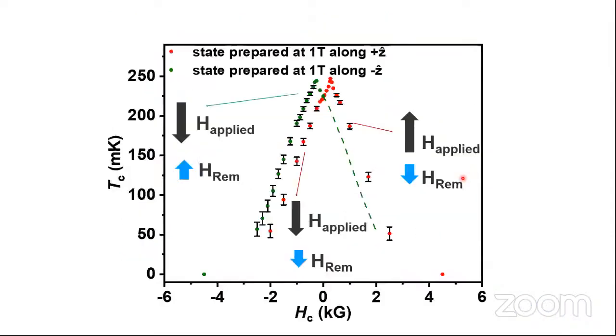So now, when I plot these things together, we see that depending on the cycling field, if it is along the up direction, then I have a remanence field which is in the down direction. And if the cycling field is in the down direction, then I have a remanence field in the up direction. And this happens at the interface. So from this phase diagram, we can conclude that the idea of the formation of a negative remanence at the interface is valid because the observation is consistent with that.